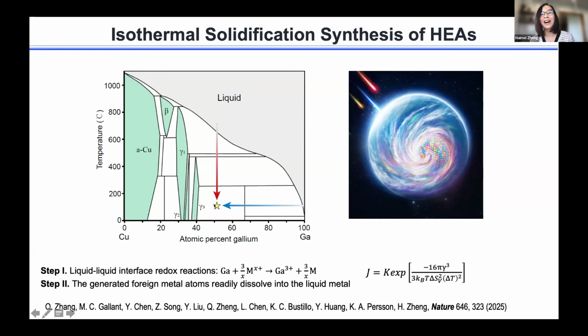This is also showing just the concept of controlling the composition. This shows diffusion. There's no diffusion barrier if it is reduced as single atoms, and this gets oversaturated quickly, getting into a supercooled state. The composition can be controlled by the precursor concentration. We can vary the composition based on the precursor and also the liquid metal composition we begin with. In addition to pure gallium, we can also use gallium indium tin as a precursor. Got it. Thank you.